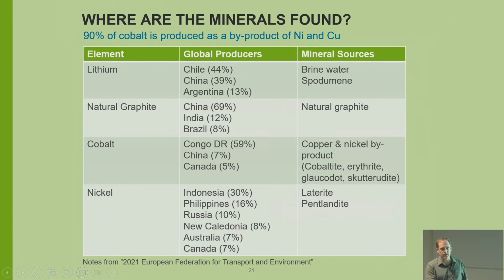Cobalt, again, we do actually have some cobalt. I'll have a slide on this too. We do have some cobalt reserves in the United States, but for the sheer size of the lithium-ion battery market and what's being projected, I'll show you that later, we need to import cobalt or keep looking for it. But a lot of your cobalt is coming from the Democratic Republic of Congo. It used to be Zaire. It's always a byproduct of copper and nickel production. It occurs with copper and nickel. So in the Congo, they have a lot of copper deposits, and that's how they're getting the cobalt. Nickel is coming from laterites and pentlandites, so mainly from Indonesia, Philippines, and some from Russia.